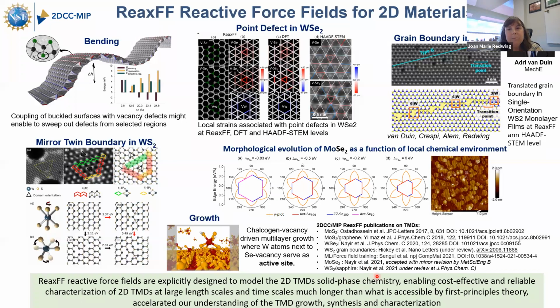So in the theory facility, we're going to be expanding our activities in the use of ReaxFF reactive force fields to simulate the structure and chemistry of TMDs and other 2D materials. And as I mentioned previously, this work is led by Professor Adri van Duin, and Adri's group has developed force fields for most of the common TMDs, such as the tungsten and molybdenum sulfides and selenides. And they've been applying the force fields to simulate defects and grain boundaries in monolayers, and to also look at things like the crystal shape of TMD domains as a function of the growth conditions and the local chemical environment. And that's provided significant insights into the growth process.